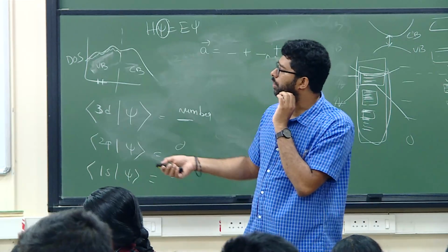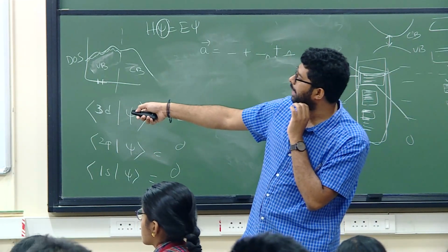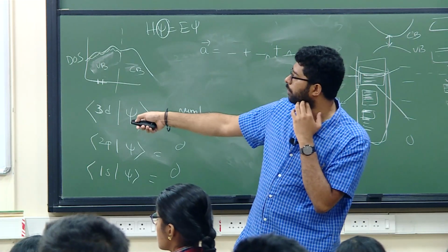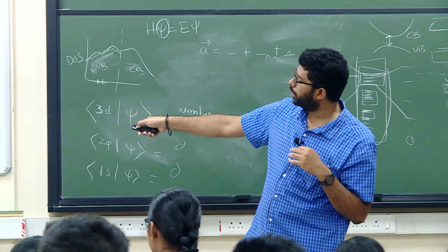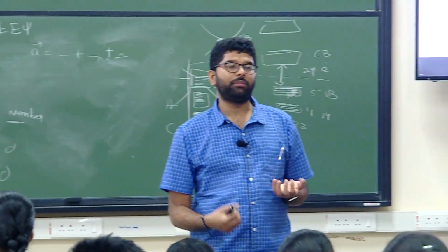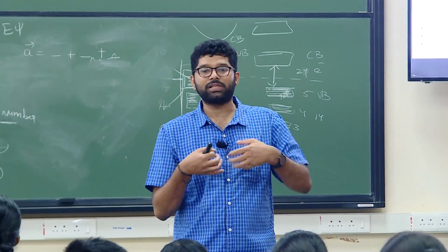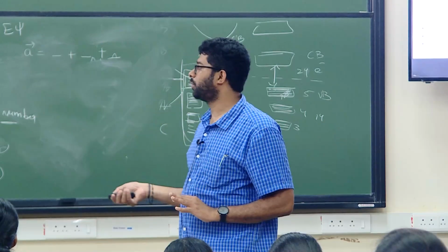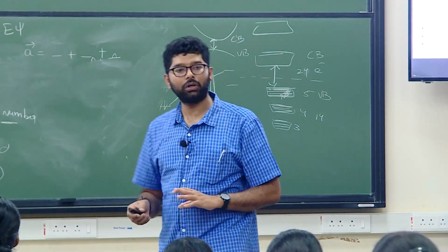So by this, if I am considering, you can see certain materials are reaching close to 0, certain others are going negative. So the ones that are going close to 0 are the ones which are good. Negative means there is some agglomeration between these ones and they are going to form dendrites. So those are not useful for us. I wanted to consider only the ones that are going close to 0.